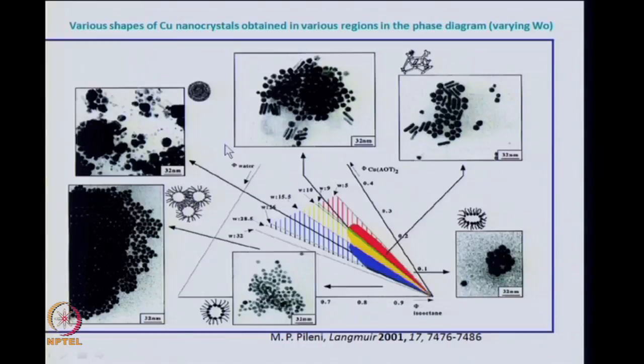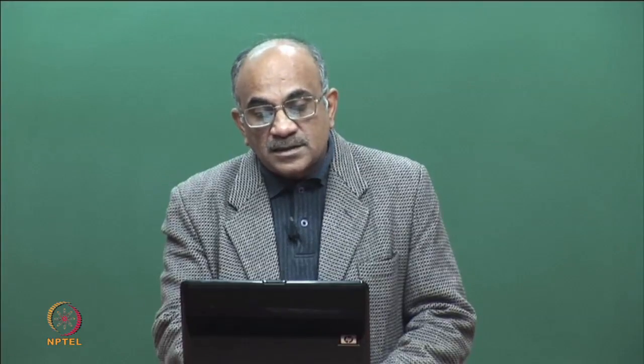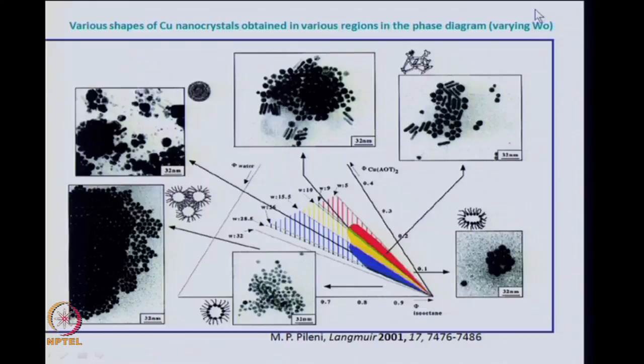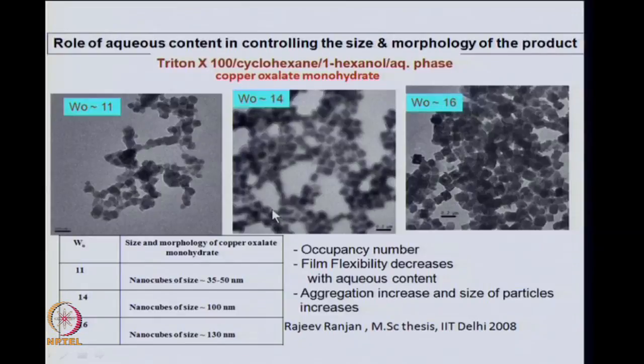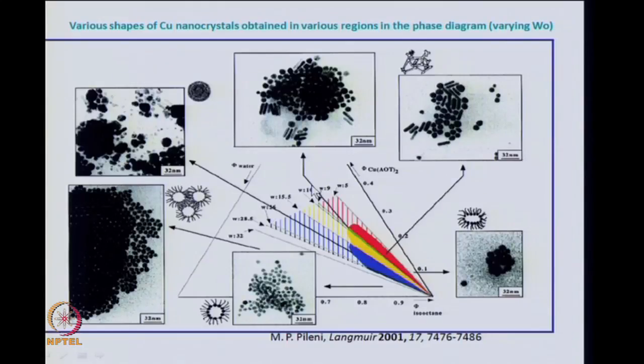So, this is another example of how using different W0 parameters. This is for copper nanocrystals. We were showing in the earlier slides copper oxalate or nickel oxalate, these kind of nanostructures. This is a slide where you see just copper nanocrystals with varying W0, and you see different types of size and shape. So, you have spheres for W0 equal to 32, and you have these kind of particles when you have W0 equal to 28, and when you have W0 between 9 and 10, you seem to get this kind of rod and particle type of mixtures for copper.